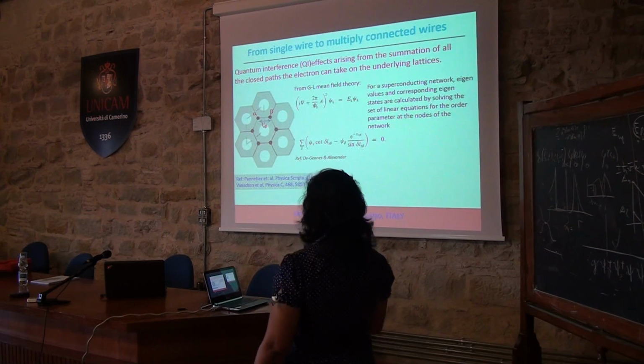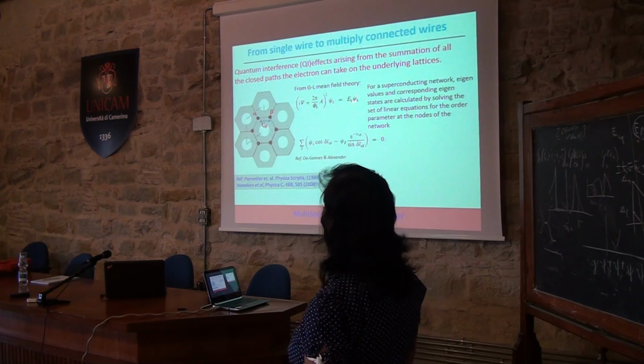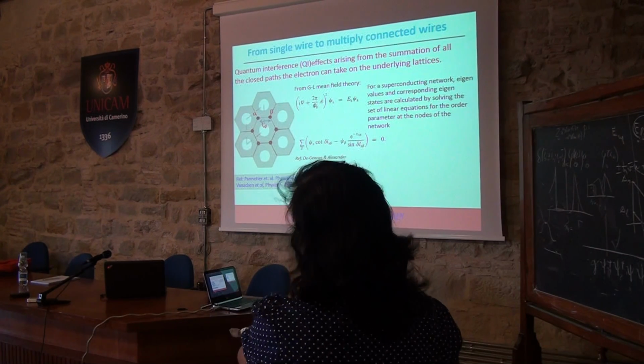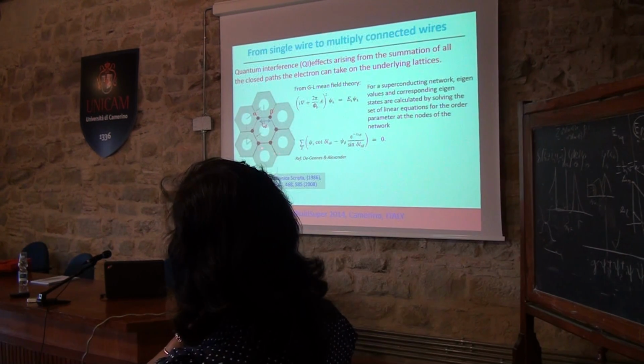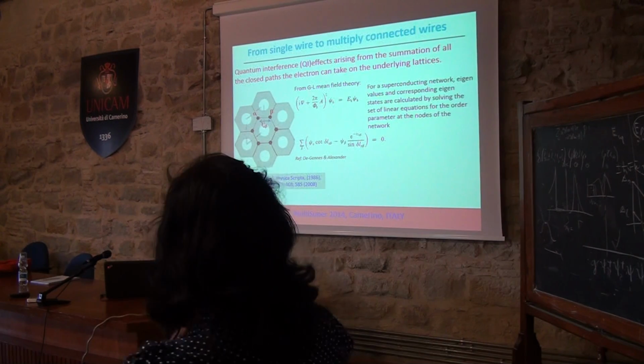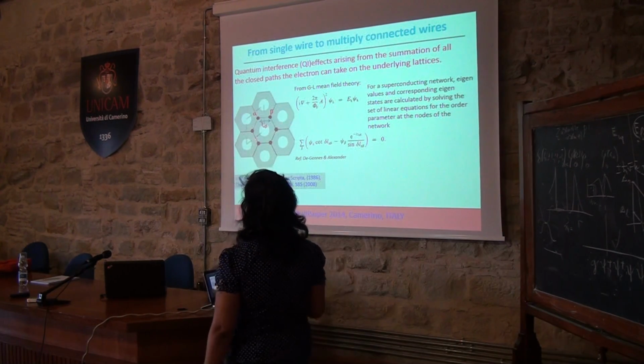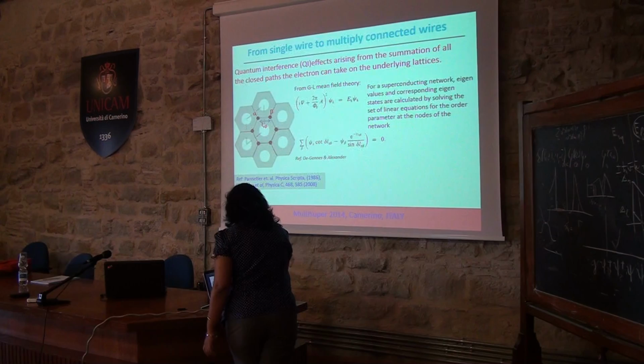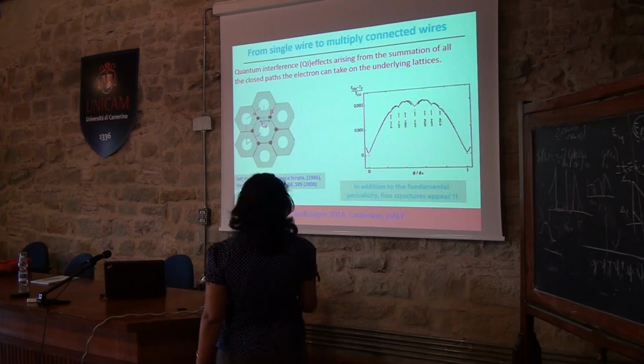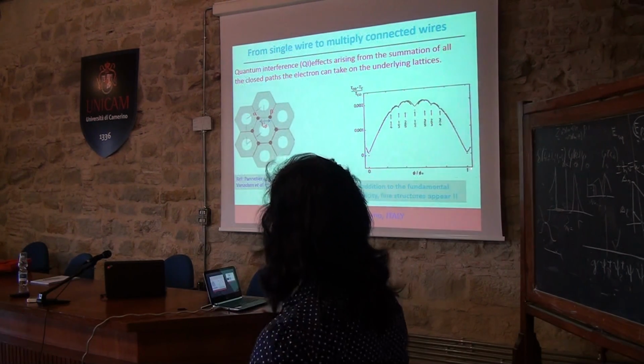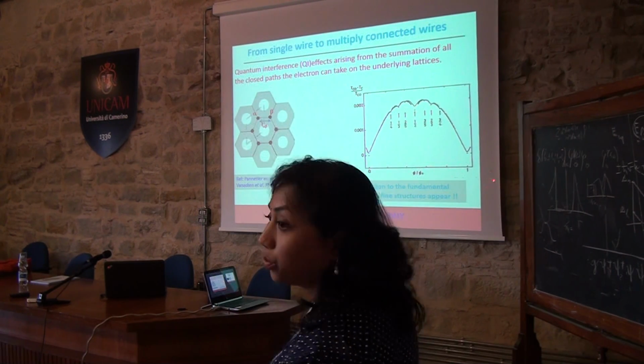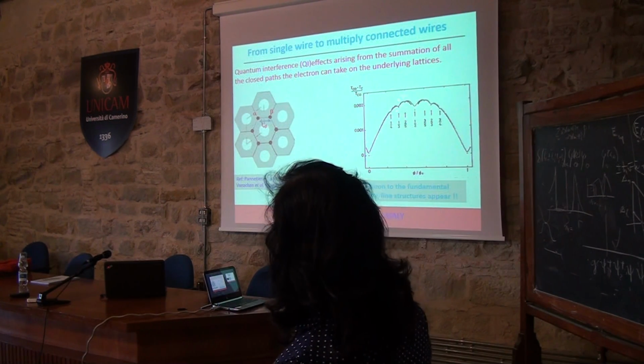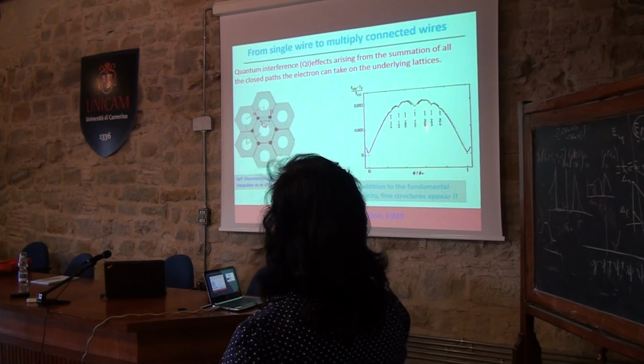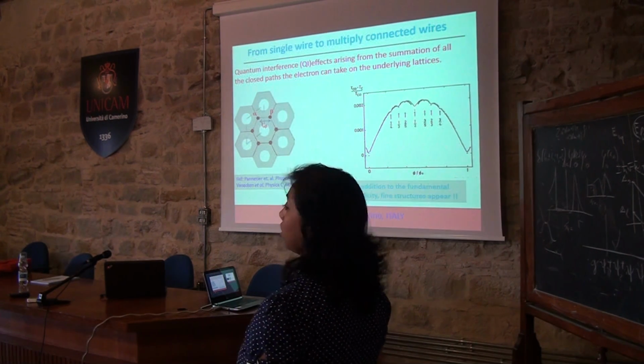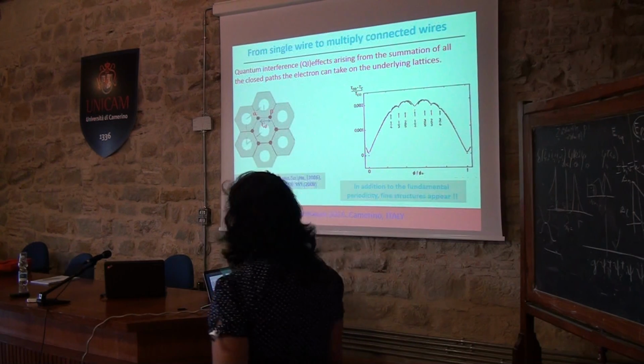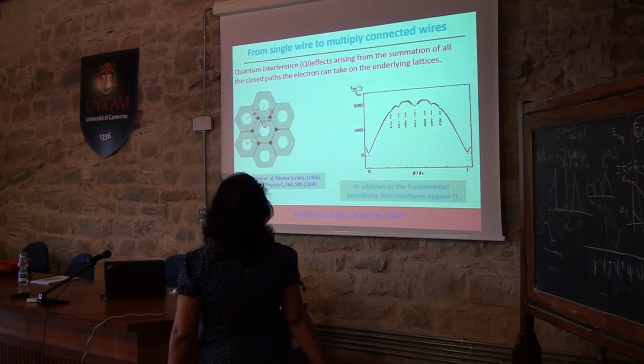The quantum interference effects arise because of the summation of all the closed paths the electrons can take around the underlying lattice. People did these calculations around different lattices. What they noticed is that in addition to the strong period I spoke about, the period proportional to a flux quantum, you start seeing finer structures. This is the classic signal of matching effect in a wire network. So you start seeing fractional vorticity.